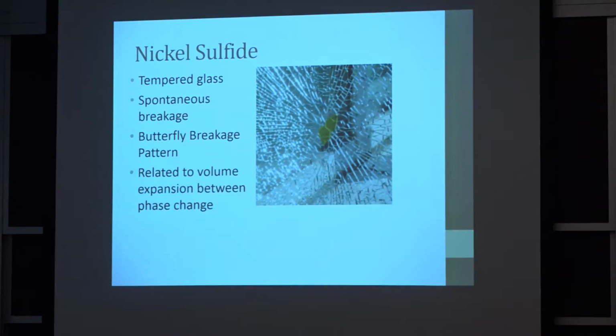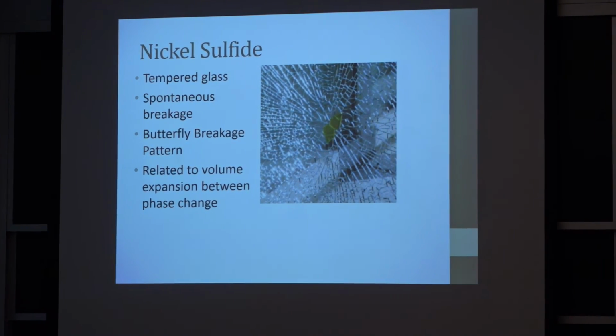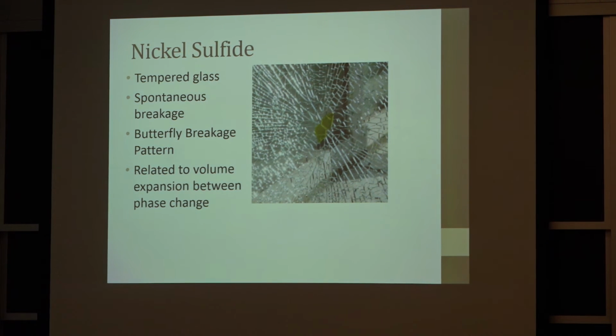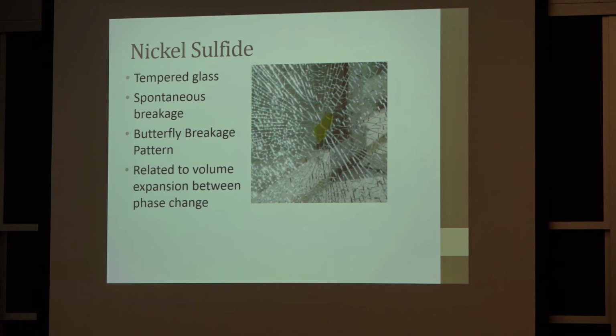The next type of inclusion I want to talk about is nickel sulfide inclusions. Now, this is typically only found in tempered glass. Tempered glass, similar to how you can temper or anneal steel, is where you keep it at a certain temperature that removes any stresses in the glass, and then you can strengthen it afterwards. If you don't leave the glass in the tempered state at either a high enough temperature or for long enough, you can get inclusions that don't diffuse out of the molten glass. When the glass solidifies, these inclusions get caught at about the mid-thickness of the glass. So it's important to note for the float glass process, you do have a thickness limitation.